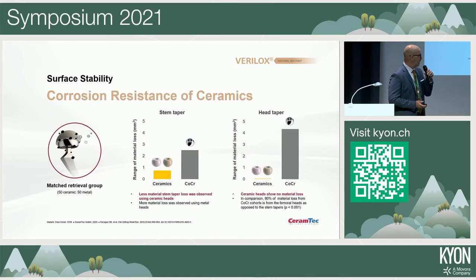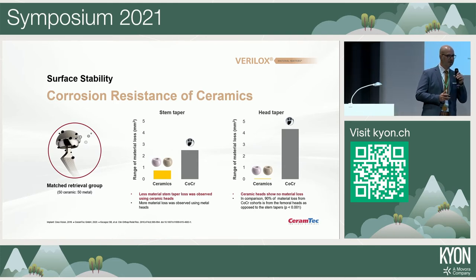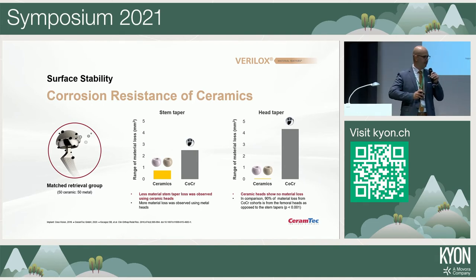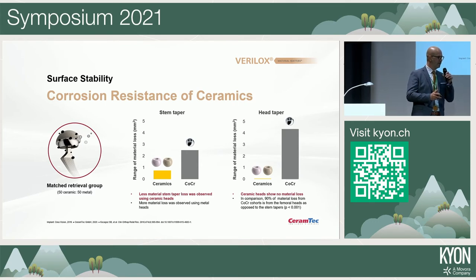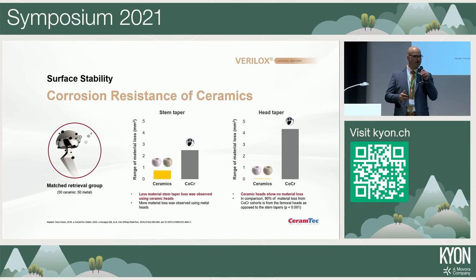The next topic of interest is the corrosion resistance of the material. If we combine different materials like ceramics and metals, as we do in modular implants, we have a risk of corrosion at the interface. And once again, there's a difference if you combine ceramics with a metal than instead combining metals among each other. And that was a test here where we compared the results of ceramic heads on titanium stems and cobalt chrome heads on titanium stems.